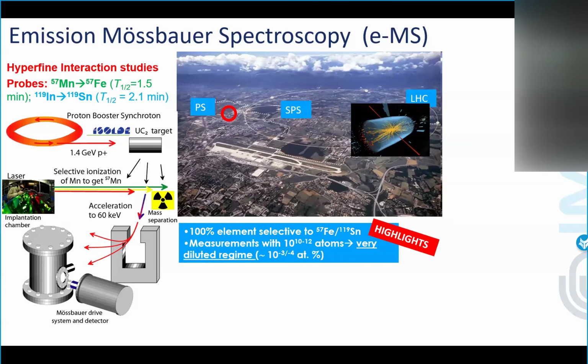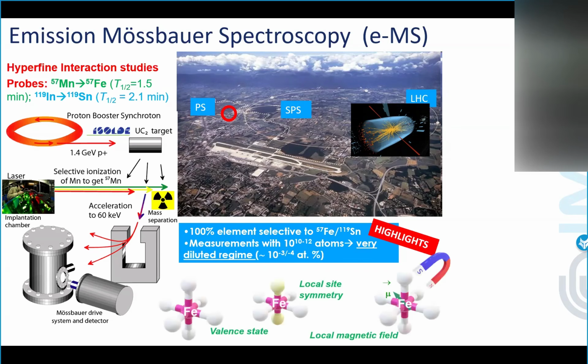The main highlight of this method is that it is 100% selective to what you put in. So you just see what you are implanting in your sample, and you can make useful spectroscopy in an extremely dilute regime. Up to 10 to the 12 atoms is what you need, which corresponds to 10 to the minus 3, minus 4 atomic percent in your implanted sample to have a good quality spectrum. And then you probe the usual things, so the hyperfine interaction that you are interested in.